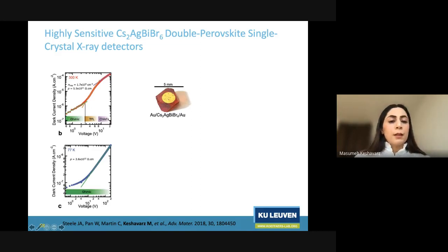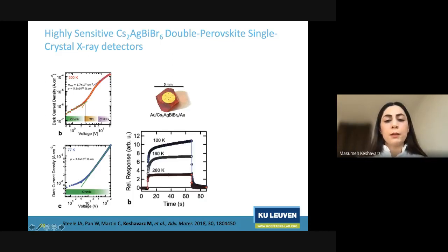Then we looked at their IV characteristics, in which at room temperature we could see all three regimes: the ohmic, which is the linear, then when we increase the voltage, we reach the trap filling limit, which is the regime where we are filling the traps. And then when we increase the voltage further, we reach the Child's regime, where all the traps are already filled. At low temperature, within our measurement window, where we can only apply 200 volts, we could only observe the linear, ohmic regime.